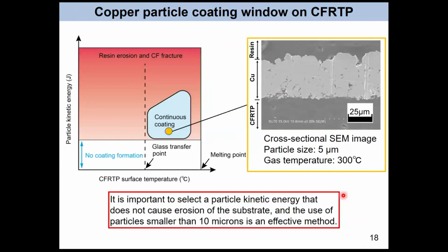So I drew a simple map of the coating window for CFRTP. When increasing the particle kinetic energy, which in this presentation means the particle size effect, severe carbon fiber fracture and resin erosion occur. And when we change the gas temperature, it means the surface temperature changes. Over the glass transition point, we can get a continuous coating.